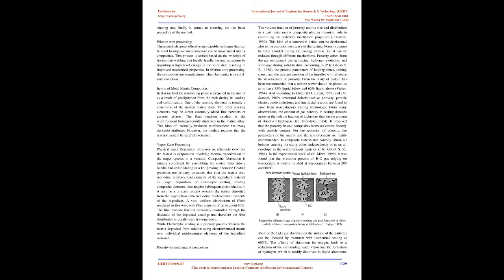Porosity in metal matrix composites. The volume fraction of porosity and its size and distribution in a cast metal matrix composite play an important role in controlling the material's mechanical properties. Hashim, 1999. This kind of composite defect can be detrimental also to the corrosion resistance of the casting. Porosity cannot be fully avoided during the casting process, but it can be reduced through different mechanisms.